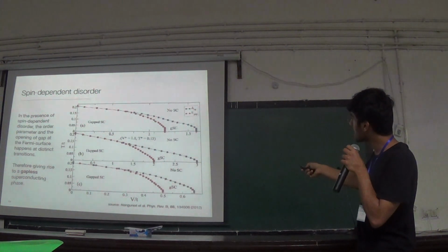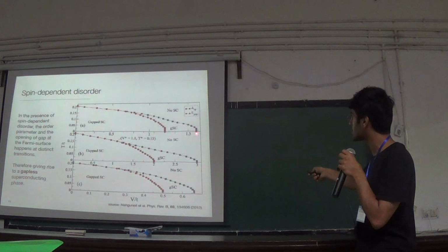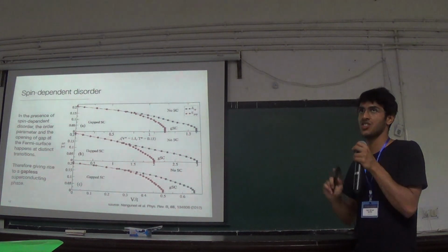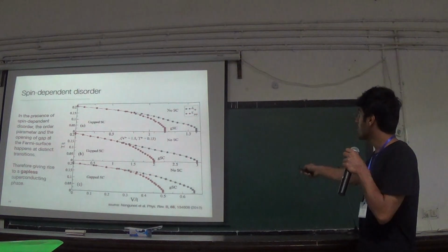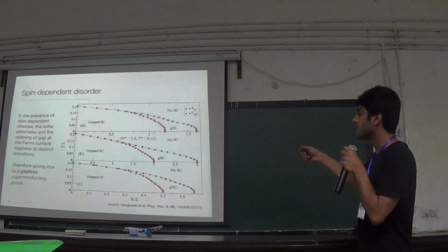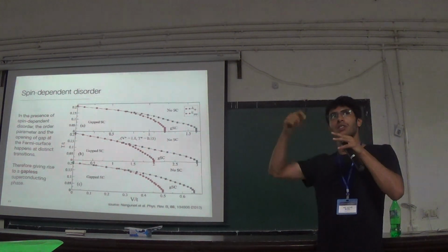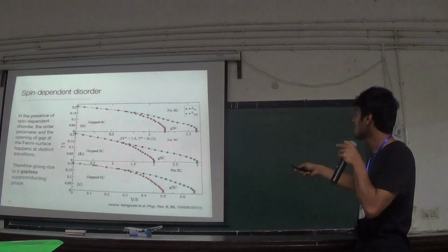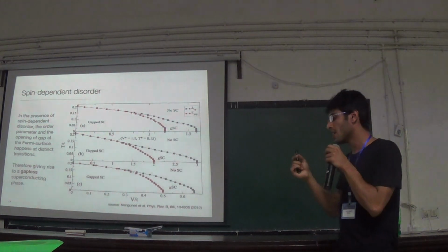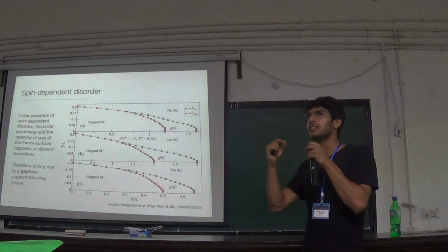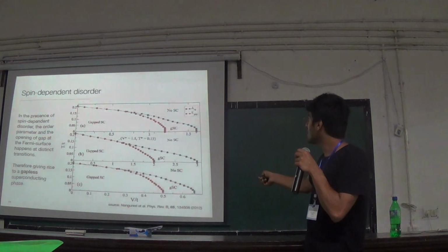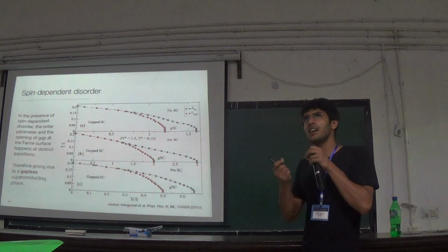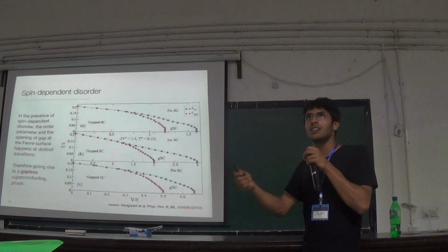But what exactly you get is that a gapless phase appears in the superconductor. That means your order parameter has changed, your ground state has changed, but the energy gap in the density of states is still not there. The gap hasn't really opened up. So there's a gapless phase. That means the energy that you need to excite a Bogoliubov quasi-particle would be just the energy you need if you want the Bogoliubov to move with k momentum.